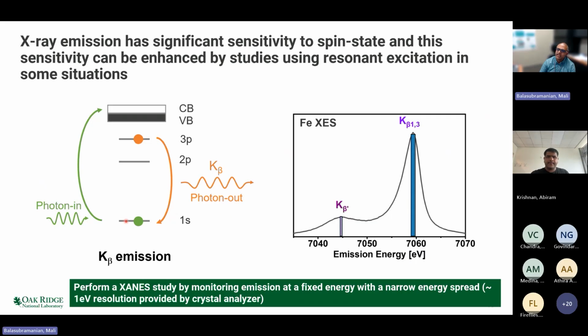So here what you do, as I explained before, is you take an electron, you put it into this sort of unoccupied density of states, which is available. And then you look for emission that comes from the 3p. By means of a crystal analyzer, you can choose a very small region. You can choose a narrow energy spread of the order of 1 eV and monitor this emission as a function of incident energy as you go through the iron absorption edge. Similarly, you can do the same thing by monitoring the K beta prime emission.